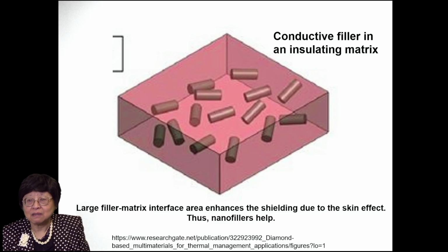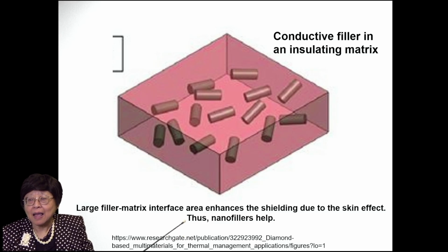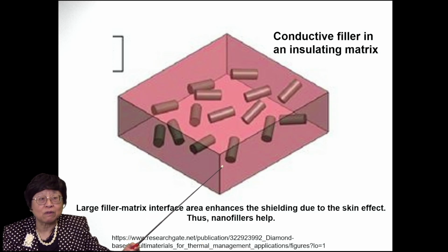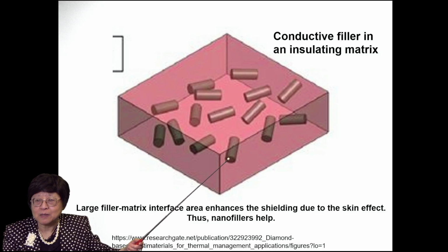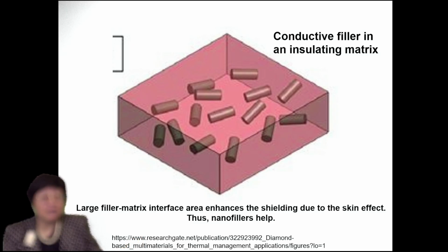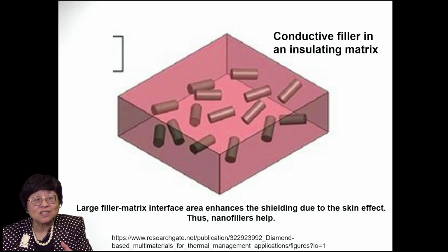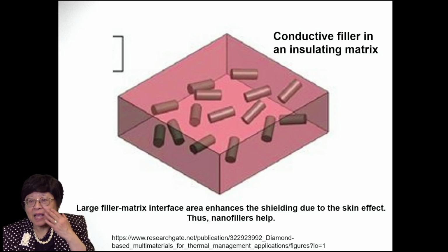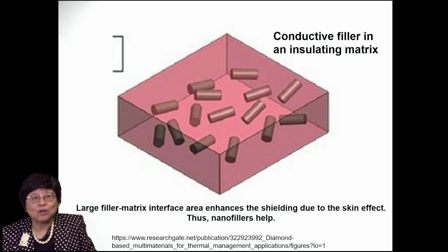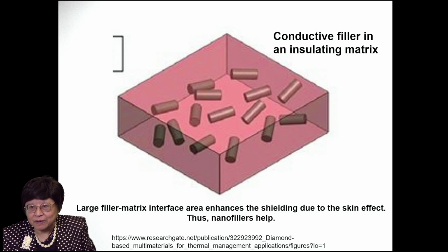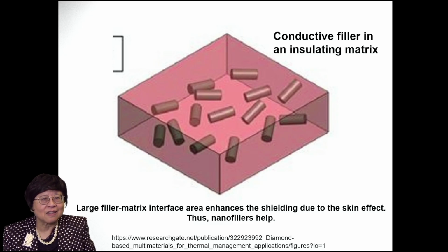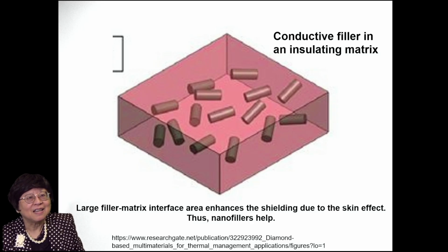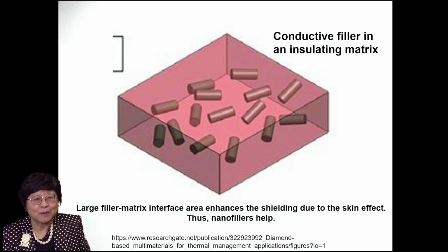So if you have a composite with a polymer matrix which is not conductive, and you have conductive filler in the form of these short fibers, let's say. And if each short fiber is big and fat, only the surface region of each fiber unit sees the radiation. The inside just sits there doing nothing. So at the same volume fraction of the filler, having a nanoscale filler would be much more effective for shielding than a microscale filler. And so I realized then that the surface area or interface area is very influential. With nanotechnology being more and more commonplace, the use of nanofillers become more and more feasible.